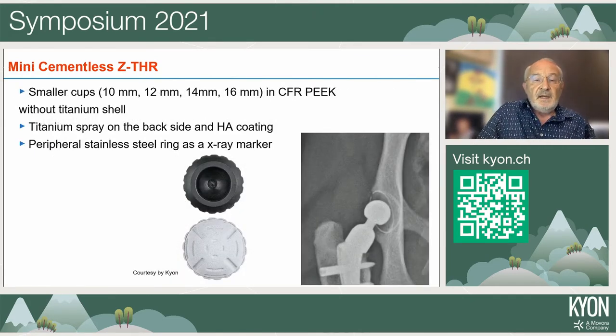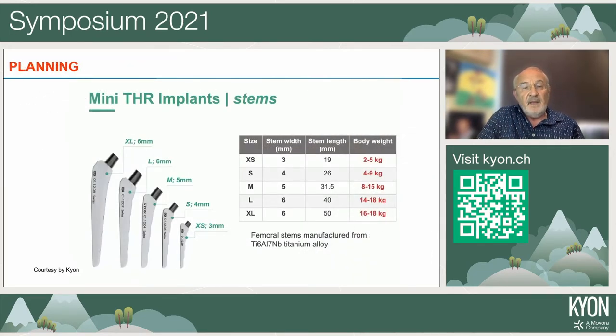The smaller cups, the 10, 12, 14, 16 millimeter, lack the peripheral titanium shell. So they are all made by carbon fiber reinforced PEEK with just a small ring of metal in the periphery as an X-ray marker. Those small cups are the more tricky to be set inside the acetabulum because they really need a very, very precise acetabular reaming.